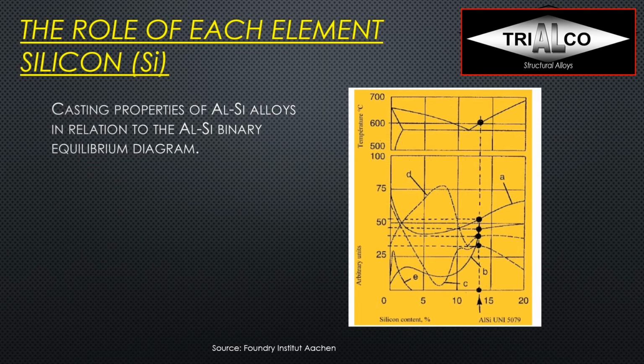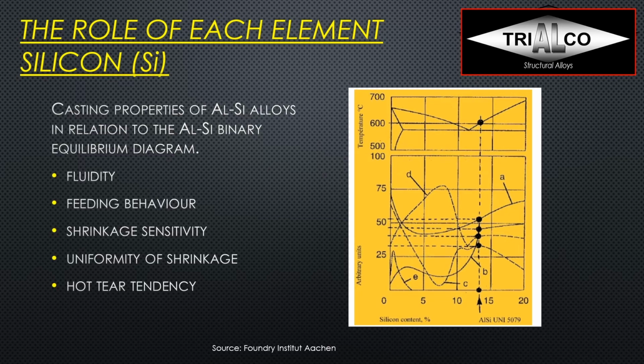Now, there are diagrams that really show all the different effects of each element, and here for silicon we can see that: fluidity, feeding behavior, shrinkage sensitivity, the uniformity of shrinkage and hot tear tendency. If we look at one specific point, like here somebody looked at 13% or 14%, so slightly above the eutectic, we can see the fluidity, that is our A here, went down first, and now we're pretty high up again, so not at 390 level, but very decent. And I can look at all the different characteristics that I would typically be looking for in a foundry alloy.